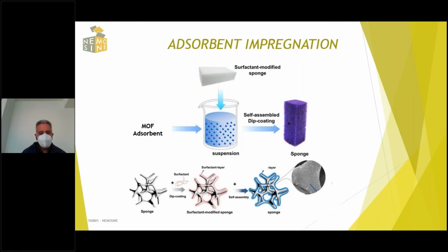First of all, we prepare a suspension with the MOF adsorbent. The important thing related to this suspension is that we need to have compatibility between the solvent, the liquid, and the MOF, to have a good dispersion and to avoid the presence of agglomerates. Then we have the foam, and the foam previously is modified with a surfactant. The surfactant may be anionic or cationic, and this surfactant allows a good bonding between the MOF adsorbent and the surface of the foam.